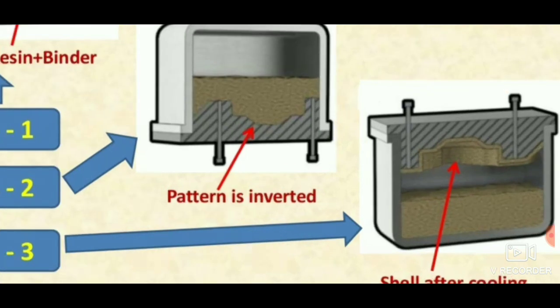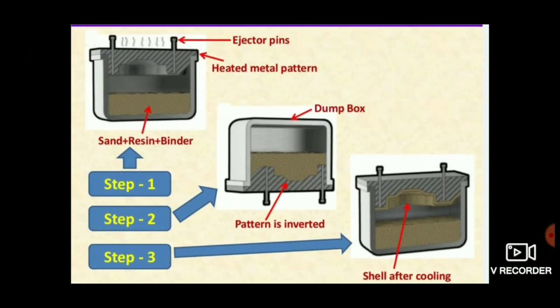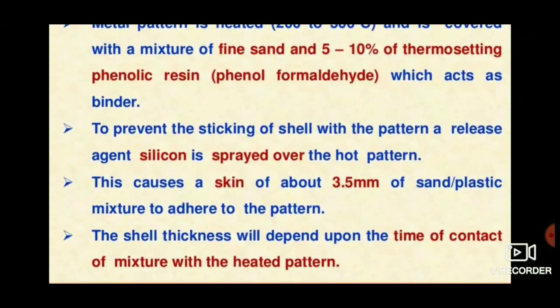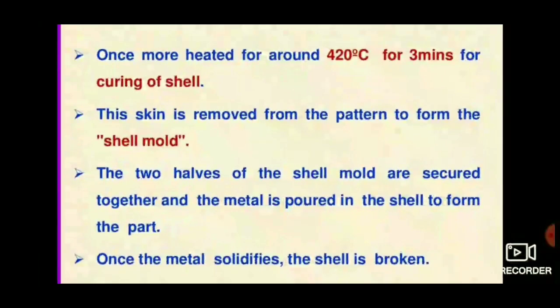This forms a layer of sand mixture over the heated pattern. A skin of about 3.5 mm of sand or plastic mixture adheres to the pattern. This thickness depends upon the time of contact with the heated pattern. After that, once more heating is applied for about 3 minutes at 420 degrees Celsius, and the shell is cured.